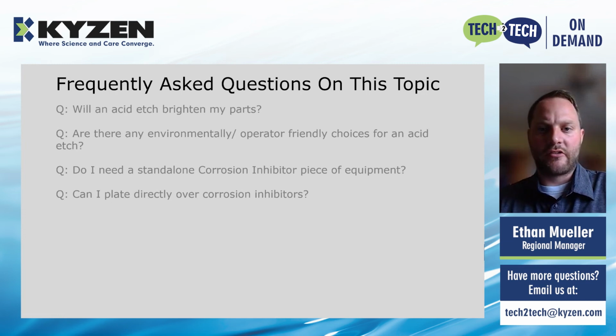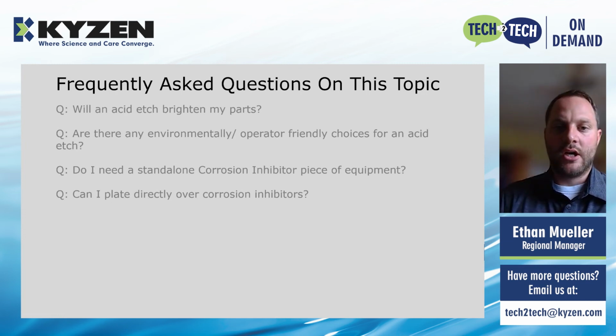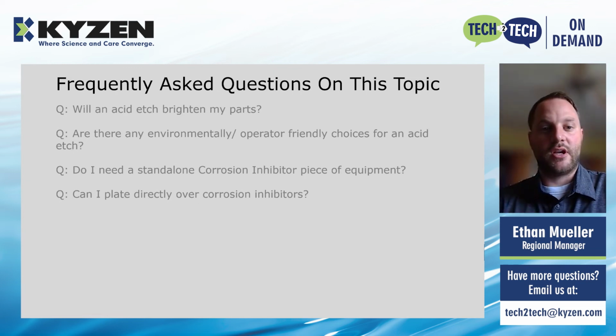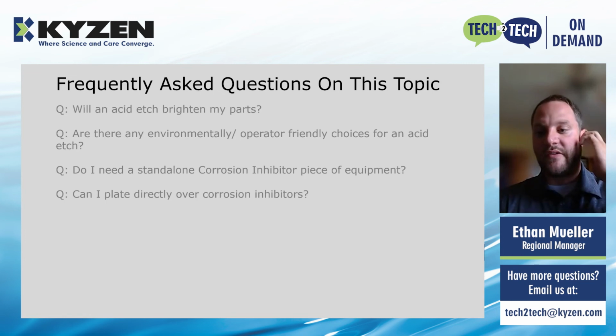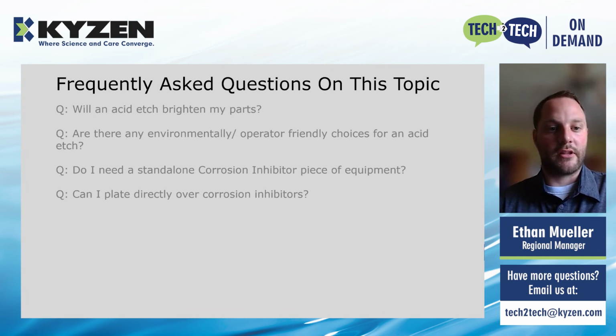Are there any environmentally slash operator friendly choices for an acid etch? Yes, citric acid tends to be a very good etching acid. It works really good for not only brass and bronze and copper. It also works on aluminum and maybe even light oxide on steel parts. And it's acidic, but it's about a pH of 3, which is relatively mild compared to some of the other acids out there which have a pH of 1. It's a little bit more friendly than that, and it's derived from citric fruit, lemons, oranges, things like that, and so it's typically considered to be environmentally and operator friendly.